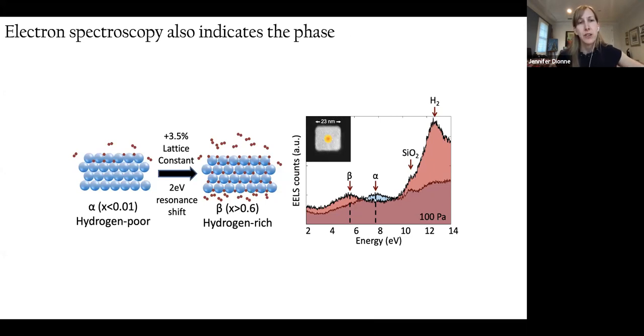It turns out that when there's hydrogen in the lattice, there's actually a 2 electron volt resonance shift of the bulk plasmon resonance. And here I'm showing you the electron energy loss spectra, where as you go from the alpha phase, you have a peak right around 8 electron volts corresponding to the bulk plasmon resonance when you excite the nanoparticle in the center. And then as the particle gets fully hydrogenated, there's an enormous shift in that bulk plasmon resonance to less than 6 electron volts. So that gives us a huge signal to noise ratio with which to follow where the hydrogen is intercalating into the lattice. And I'll mention that in my presentation, we're mostly going to focus on where hydrogen is going in, but my lab has recently developed techniques to follow also which products are going out of the particle.